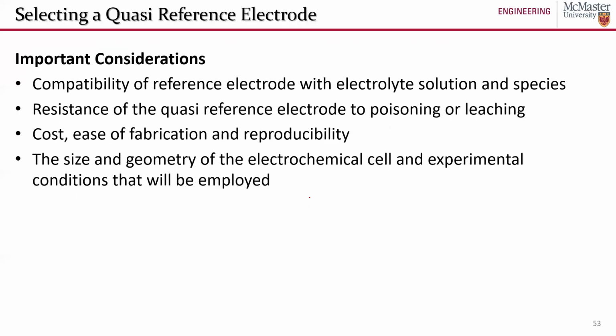I'm running a bit on time, so I'll speed it up a little bit. Essentially, we want to ensure the compatibility of your quasi-reference electrode with your electrolyte solution and species. For example, if you're going to use a gold-based quasi-reference electrode and you've got a bunch of sulfur-containing species in your electrolyte, those sulfur species are going to poison your gold electrode and pretty much ruin your quasi-reference electrode that's based on gold. You always need to consider the cost, ease of fabrication, and reproducibility of these quasi-reference electrodes, and then the size and geometry of the electrochemical cell and the experimental conditions that you're going to be employing.